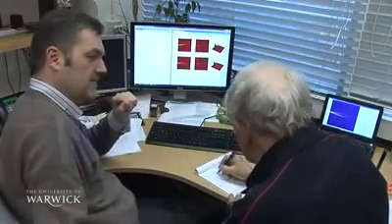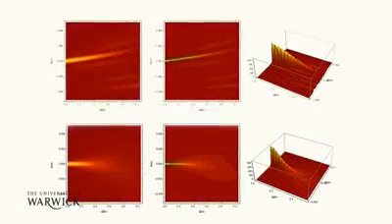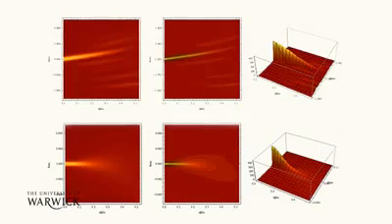In order to understand the broadening of the diffraction peaks with tilt angle, we considered theoretically various height modulations in the graphene sheets. One way we can do this is by considering rather long-range variations, and we can show theoretically that they would just lead to a broadening of the peaks. But if we consider short-range variations at the atomistic scale of graphene, we can find that this leads to side peaks appearing — new diffraction peaks appearing next to the standard peaks. We've done that both analytically and numerically, showing as a function of tilt angle how the diffraction peak would vary.